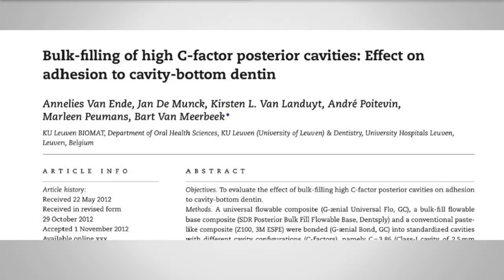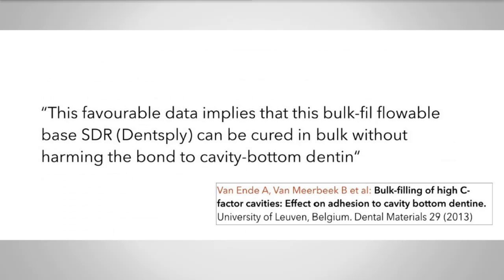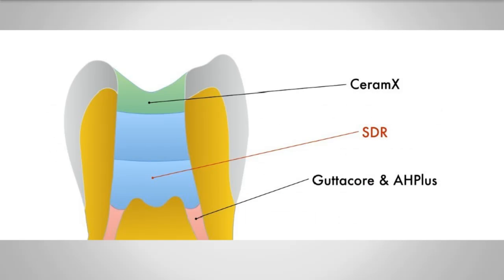So Van Ende and De Munck and Van Meerbeek and others looked at this particular problem, the bulk filling of high C factor posterior cavities and the effect on the adhesion to the cavity bottom dentine. And their conclusion, because they looked at SDR, was that the data is very favourable, and that it implies the bulk fill flowable based material SDR can be cured in bulk without harming the bond to the cavity bottom dentine. Okay, so this is a technique that I've been using now for about 1.5 years, and again, it's early days, but no issues, and the research that's come out about this would seem to be supporting this technique.